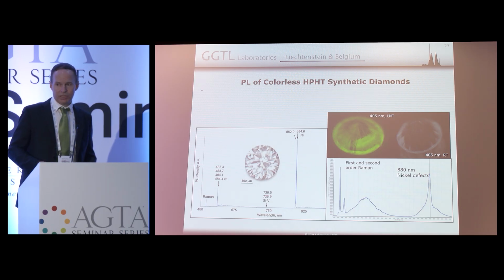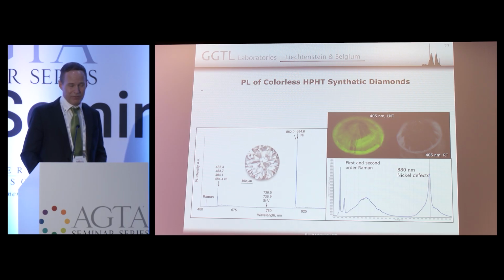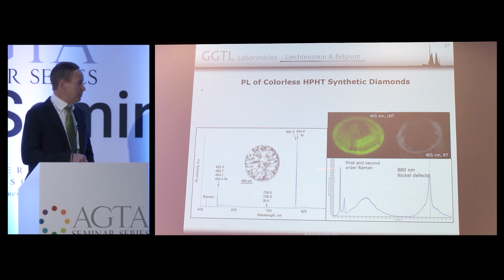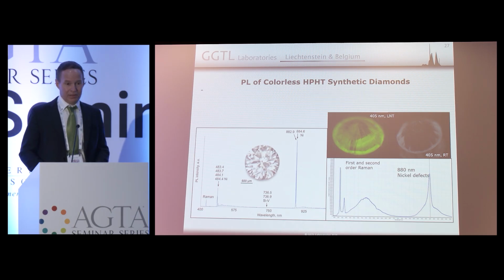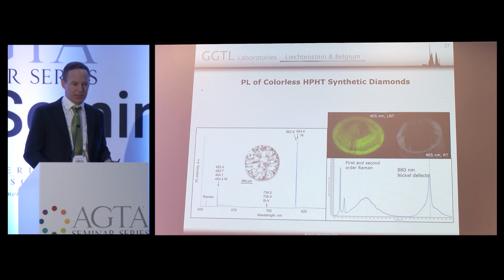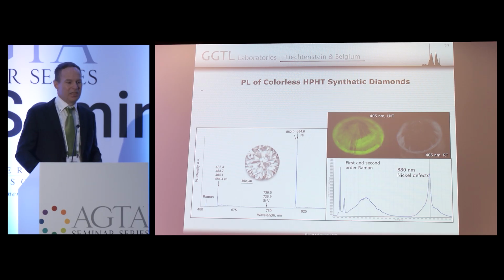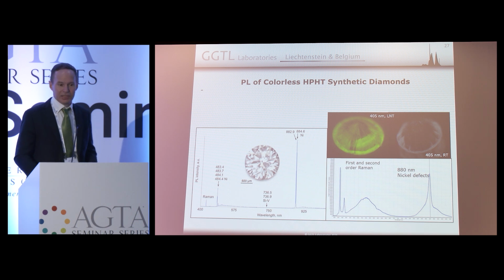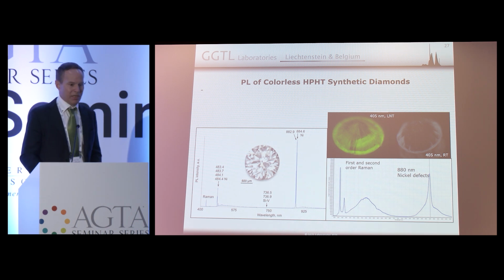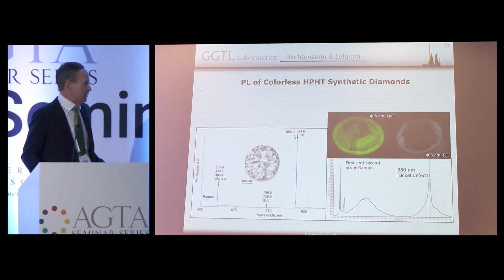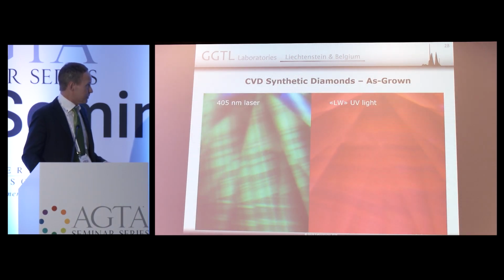But in the more recent productions, I've seen that I would say 95% of synthetic colorless diamonds don't show anything anymore. So if you go for spectroscopy, you're just going to have a flat line. And that by itself is very suspicious. So if you have a stone that at PL spectroscopy, low temperature, shows nothing, you're like, meh, that smells like a synthetic. Because in natural diamonds, you do generally find defects that are detectable at low temperature spectroscopy.